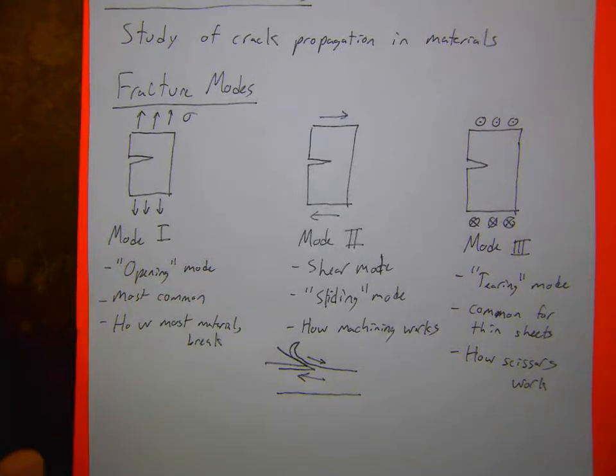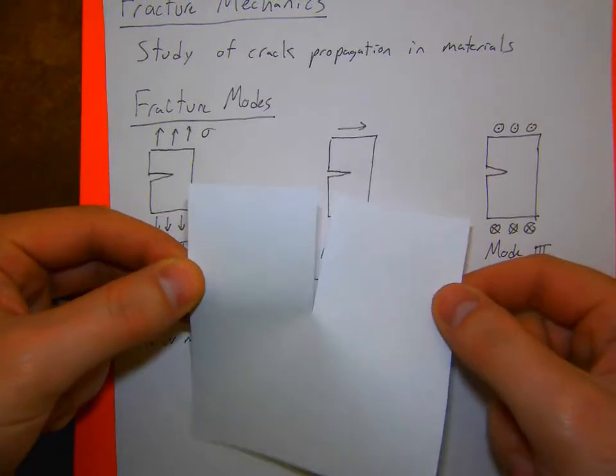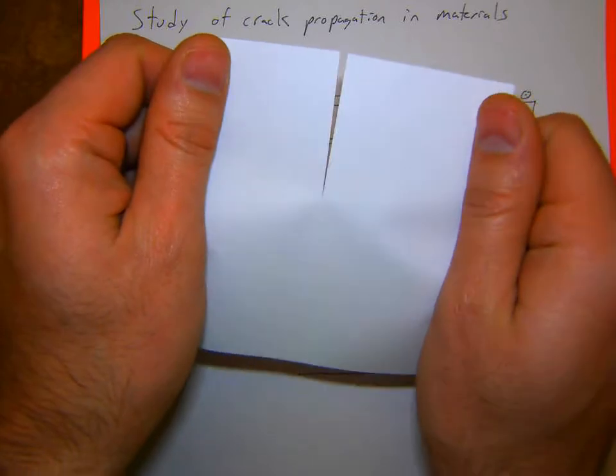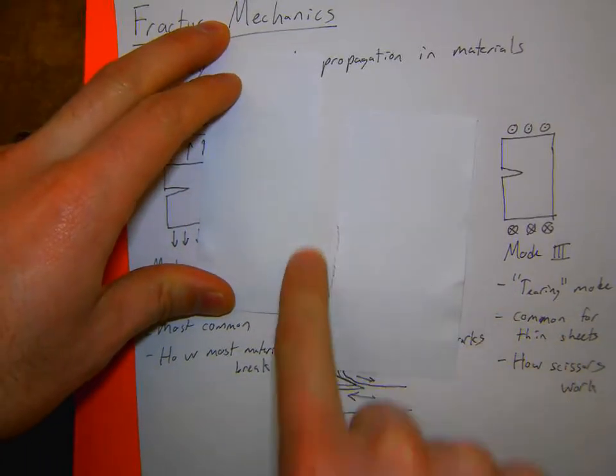So you can imagine now, so now we have these different pieces of paper. I'm gonna show you all three and I'm gonna have you check one of them out. For these different failure modes, there are different crack propagation pathways that generally take place. So mode one, which is the easiest one, you can see now I have my sandwich piece of paper. What I can do is try to pull uniformly on this surface, and I should see a nice clean fracture go through the material. So the max stress is there at the notch, and it propagates down and along there.